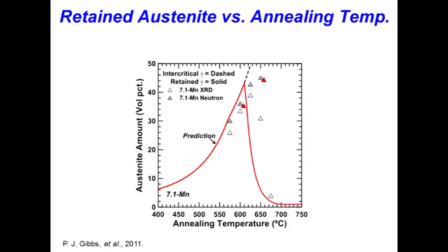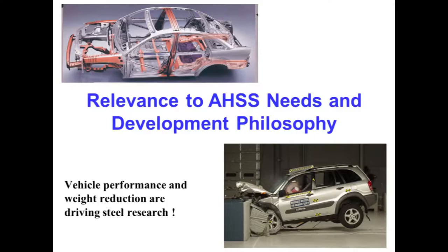This is actually how it worked out. So this is a 7 manganese, I think 0.1 carbon steel. This is the predicted austenite fraction as a function of annealing temperature, again assuming full manganese partitioning between the phases. This was a long annealing time. And these are the experimental data showing that this model was helpful to understand the behavior of this other class of materials. So it's a very exciting time in steel development now. I think I'll go on the record as saying this might be one of the most exciting times for steel development ever.